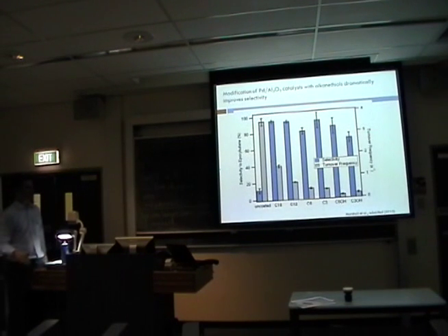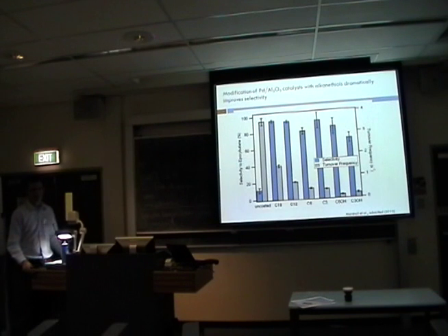Okay, so what we can see is that when we use these self-assembled monolayer coatings, if we tailor them in the right way, then we can achieve, this is the selectivity toward the desired product on a typical catalyst, it's about 11%. On a typical industrial catalyst, this is palladium supported on alumina, but you could use a variety of different metals, and you get about the same result. This is a very difficult reaction to do selectively.